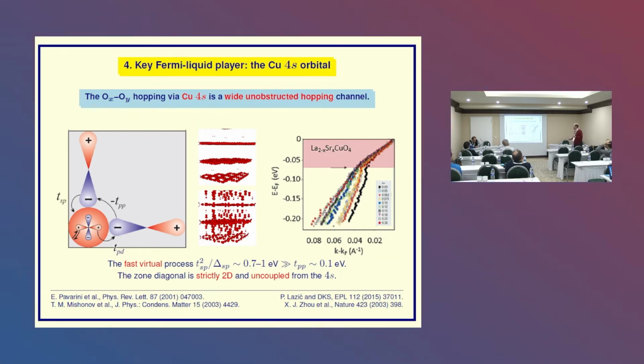Okay? So essentially, what we believe, this is a narrative. This is not something which could in principle be proven by calculation, but this calculation has not been done. We have here this fact that this is discontinuous, and this gets more and more continuous as you go to higher and higher dopings. This actually corresponds, we believe, to the transition of the copper-oxygen bond from ionic to covalent, the dp bond, okay?